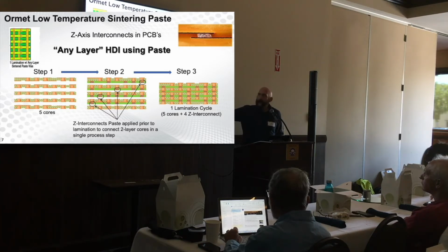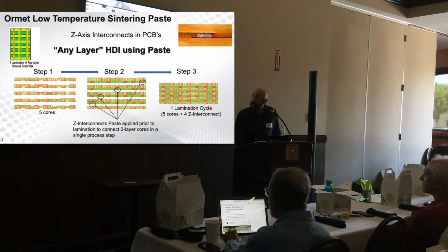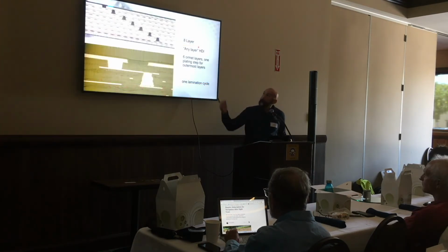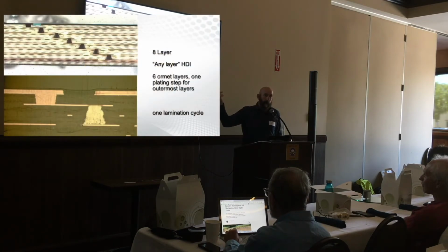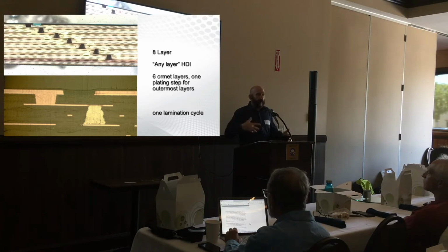A pure any layer, this is somewhat theoretical. I can't think of a lot of designs where you'd have to do this, but actually, we did. It was 16 layers, and it actually worked really well. This is a vehicle one of my customers did for me. This is using Itera MT40 as the dielectric, and one lamination cycle. So really, the outermost are traditional copper-plated shut vias, and all the internal vias are Ormet. This is a simple board, but you have complete unrestricted via placement. You can put vias anywhere you want. For high-density boards, it's amazing what you can pull off.